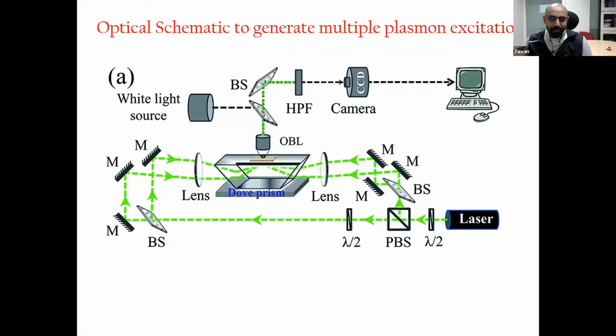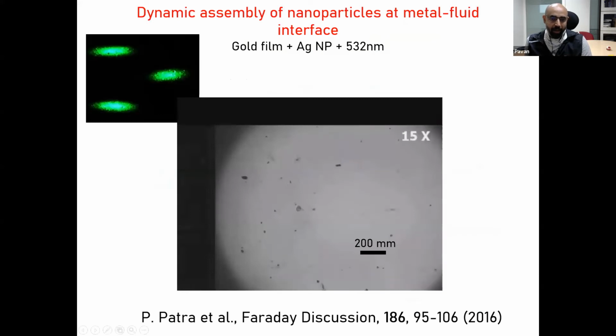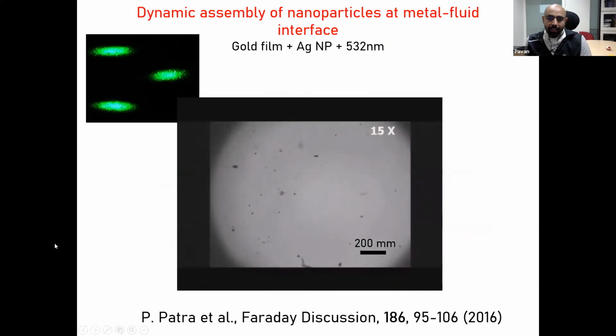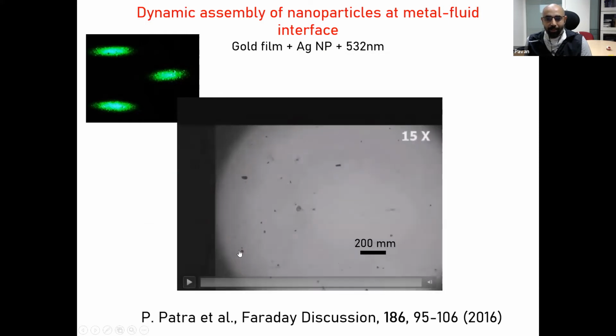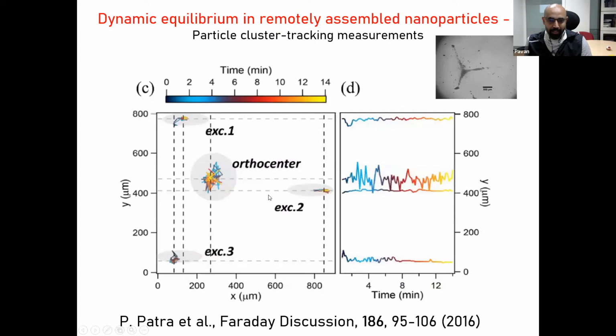Furthermore, you actually can extrapolate it to multiple beams, which creates some very interesting situations. For example, you now can take an isosceles triangular geometry, and what you observe is this. Now you start observing assemblies, of course, at the vertices of the triangle. But in addition to the vertices, you also see nanoparticles assemble right at the orthocenter of the isosceles triangle. Everybody who knows about the isosceles triangle knows that there is a point called the orthocenter, which essentially is exactly at the central point of these three vertices, and you see exactly the formation happening at the orthocenter. Okay, this is all assembled by optothermal fields because there is no optical excitation at this particular region, but a very nice assembly formation.